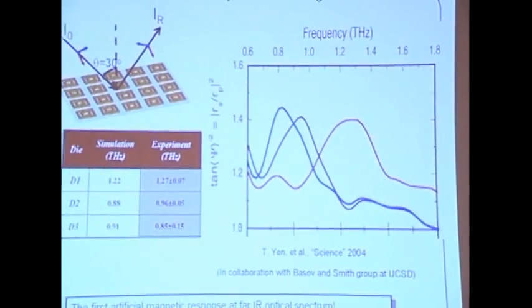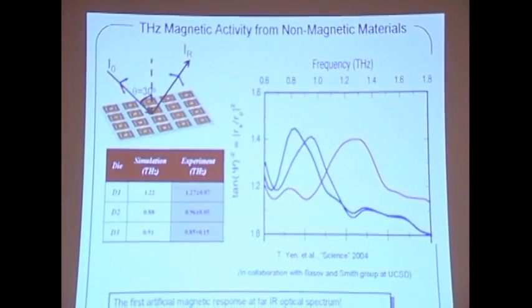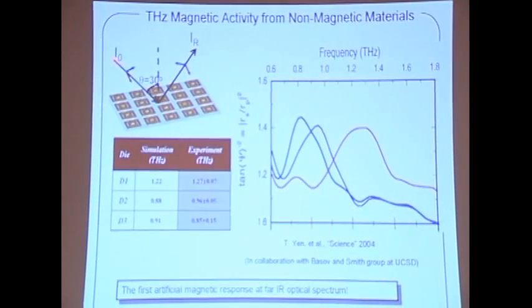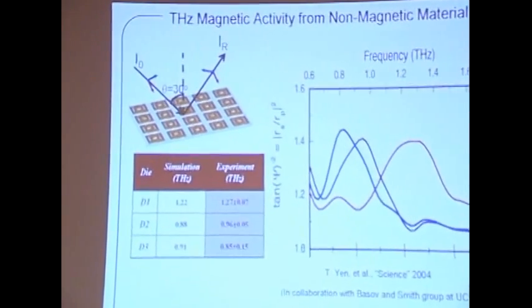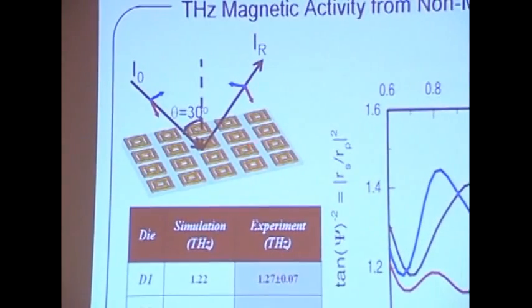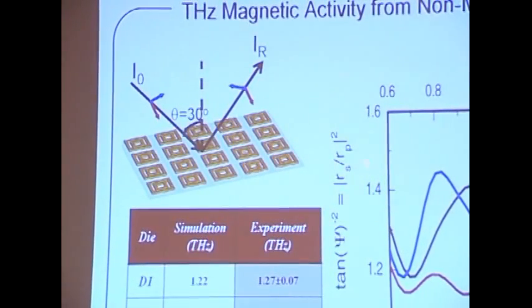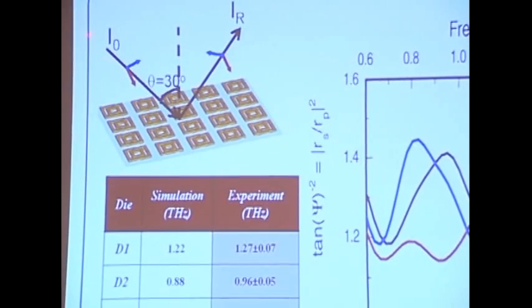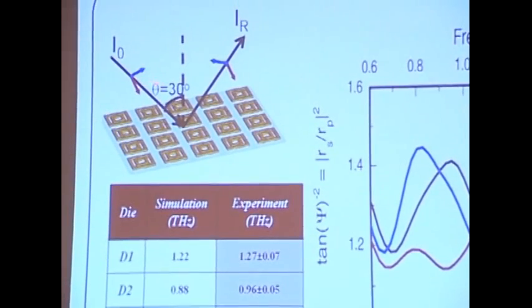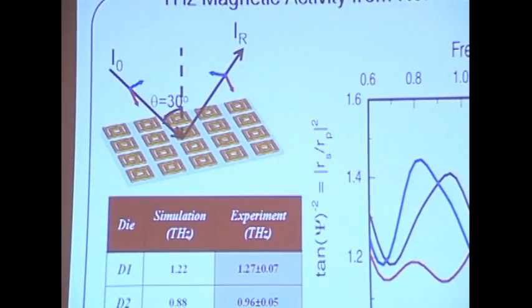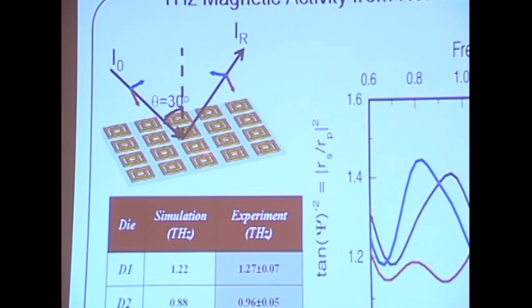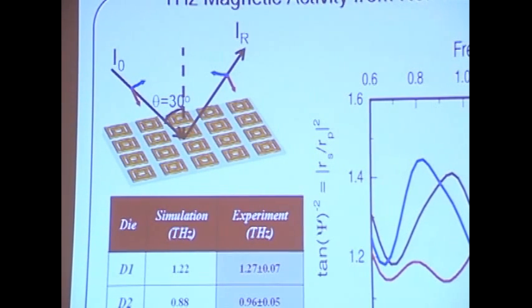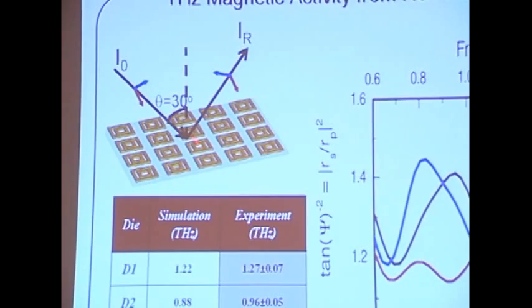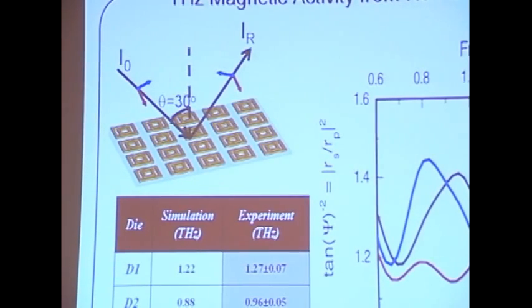The experiment was conducted with a free space FTIR measurement. You have an incident beam coming in, and we measure the ellipsometry parameters, essentially the reflection ratios of S and P. And you make sure the magnetic component, the blue one, has a component perpendicular to the ring, such that it generates an oscillating current. That also couples capacitively between the two rings, giving you collectively the magnetic response of this metacrystal.